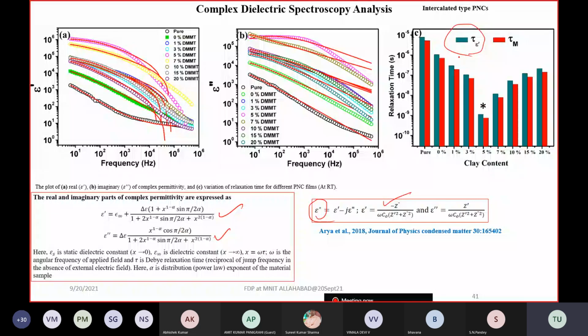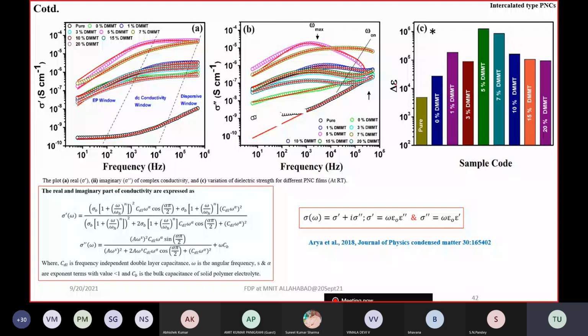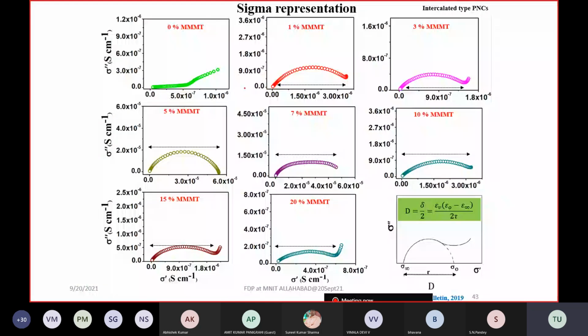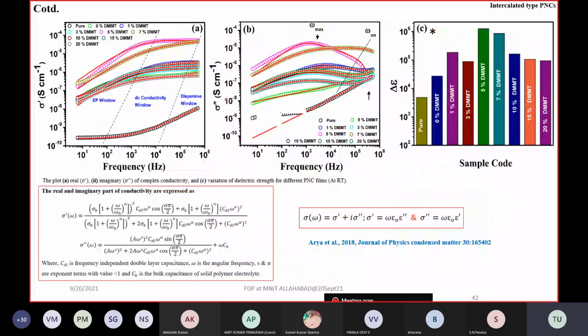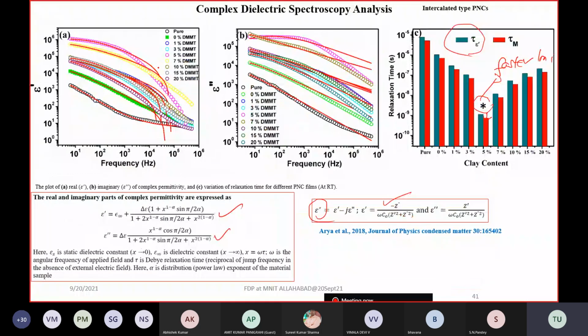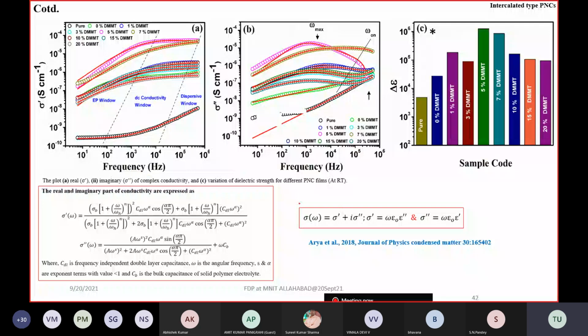For that concentration, you see the least relaxation time has come. Least relaxation time means it is providing faster ion dynamics. So in that way, the sigma representation is to be done. If you see here, from the same epsilon prime and epsilon double prime, sigma prime and sigma double prime are going to be calculated. Sigma prime is omega epsilon naught epsilon double prime, and sigma double prime is omega epsilon naught epsilon prime.